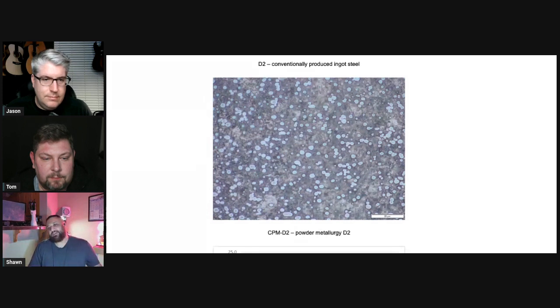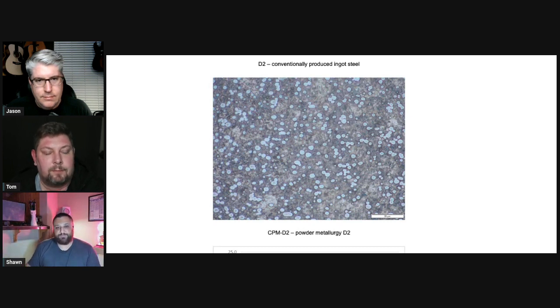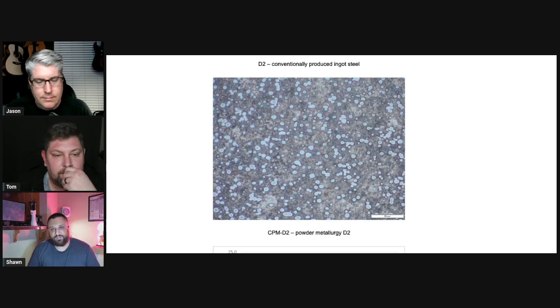They collect all the powder at the bottom. And then from there, what they try to do is they take all that powder, they collect it, and then they repress it with what they call hipping, or hot isostatic pressure, where they have this big canister, and they apply heat and they compress it, and they try to basically get it to solidify again. But then it's further solidified with more of the porosity, or basically little gaps in between, reduced by hot rolling it, which is like forging it.